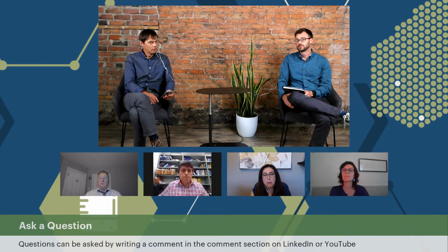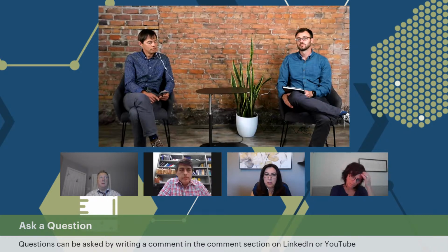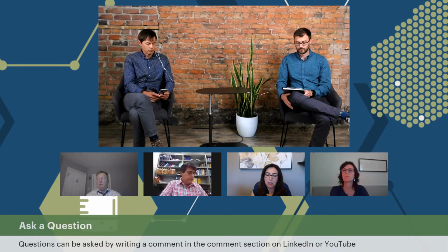Okay, thank you. Mojan, did you have any thoughts on that? I just want to add a few points. Based on my experience characterizing different lignins, the majority of the changes can be optimized during the last stage of isolating lignin from black liquor, and isolating lignin from lignin cake in terms of biorefinery. As long as the source material is consistent, for example if pulp and paper producers use softwood and keep using softwood, not mixing hardwood with softwood, and the process parameters they use to isolate lignin from the black liquors are similar, we see less variation in lignin properties. And like I tested at different times, we usually see very consistent properties if those last-stage parameters are kept the same.